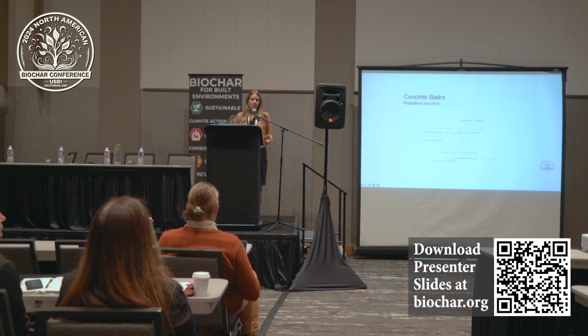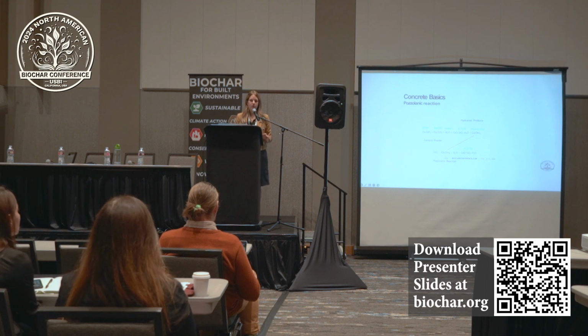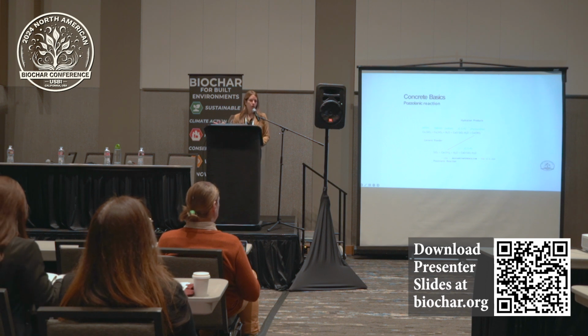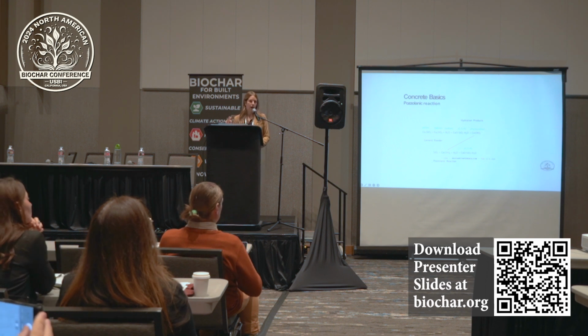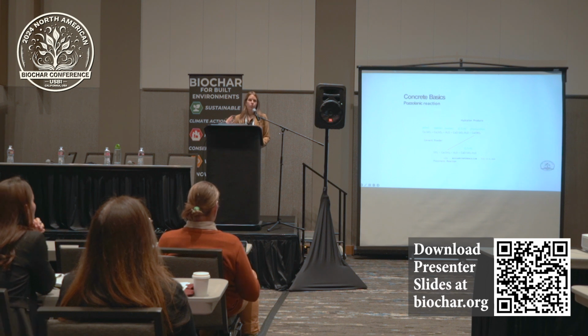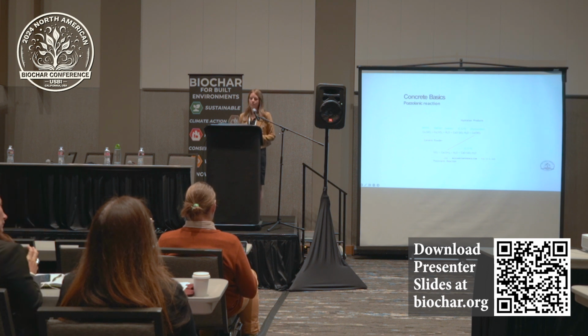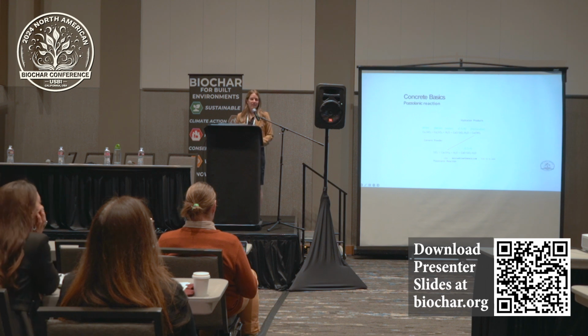So that brings me to another chemical reaction that often happens in concrete systems, and that's a pozzolanic reaction. With a pozzolanic reaction, you have a pozzolanic material, so it's something that's got reactive silica, so you have silicon ions dissolving in solution, and those silicon ions react with the portlandite from the cement hydration reaction and combine with water to form more CSH. So pozzolans are great because it takes this inert material, the calcium hydroxide, combines with silicon ions, and then forms more CSH, which again is the strength-producing material that gives concrete its engineering properties. So we really like that in concrete systems.